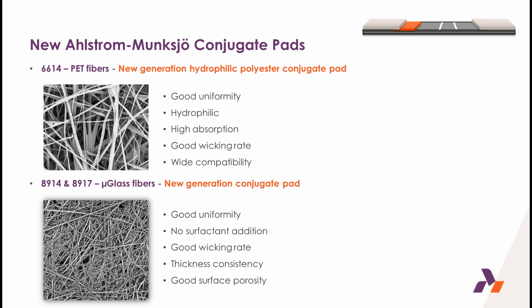This 6614 exhibits a higher absorption capacity compared, for example, to the 60-13, which means a lower volume of chemical is needed to pre-treat the same surface area. Thanks to the high pore size and hydrophilicity of the fiber structure, this material has a good wicking rate, suitable for tests requiring a rapid interpretation. Finally, this new conjugate pad fits very well different designs with a variety of reagents, such as gold nanoparticles or even latex bead.